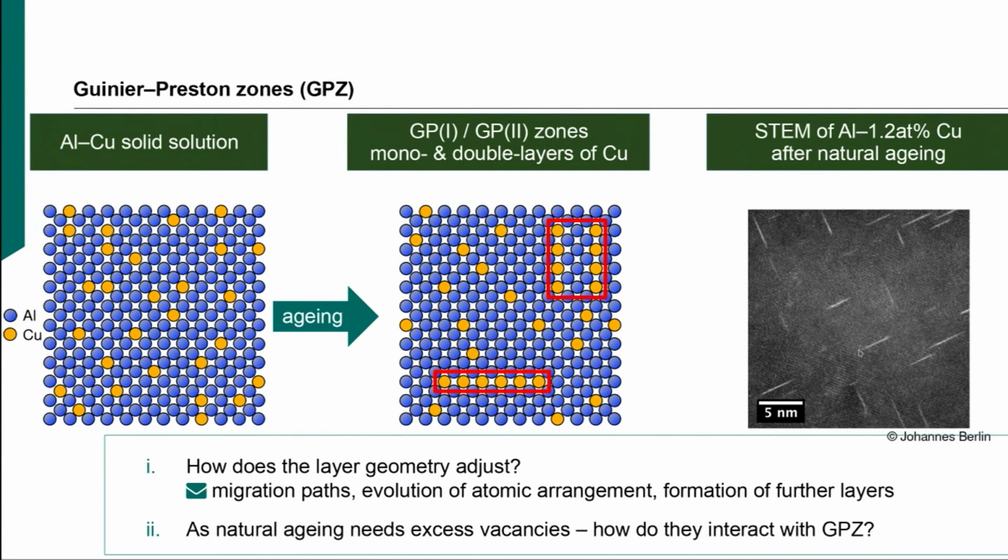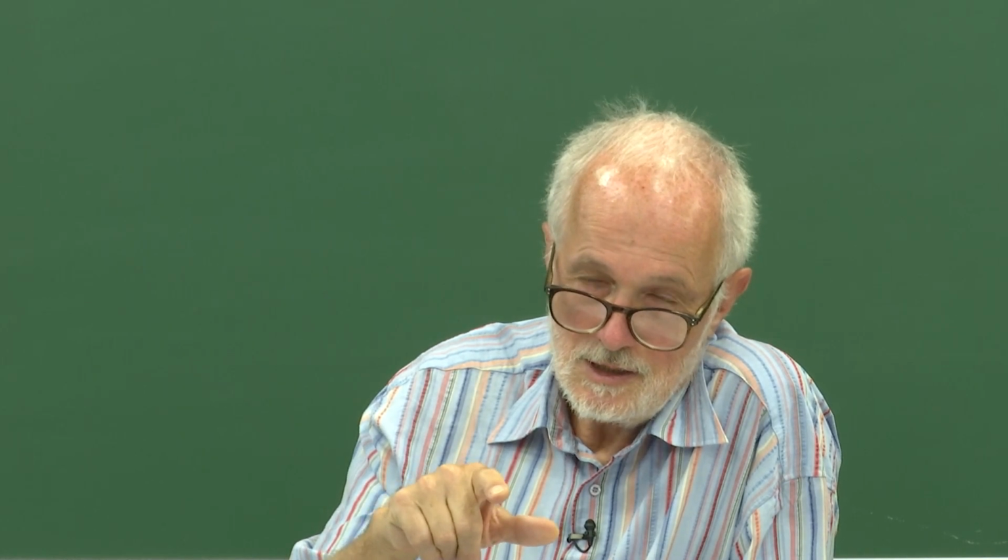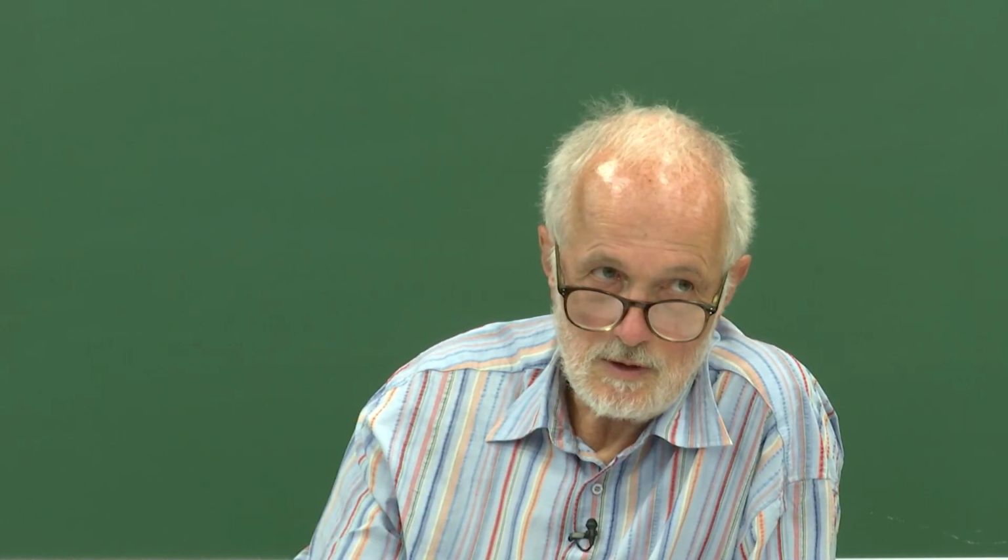Okay, so these are these Guinier-Preston zones. I showed another example where I tried to motivate why they have this nice plate shape. But here I wanted to show something else. Here, for example, you see two of these Guinier-Preston zones with a spacing of 3 aluminum layers in between. So that's an aluminum 3 copper phase. And that's indeed the phase which is one of these minimum points here. It's a GP2 or theta double prime phase in this aluminum copper system.